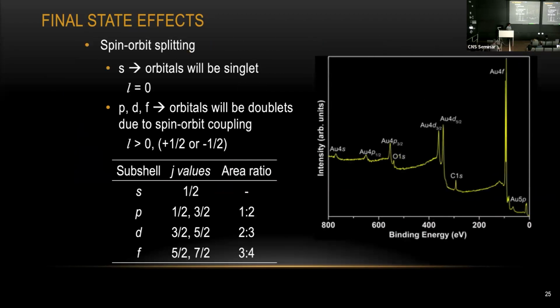And in the next couple of slides, I'm going to show you the final state effects. The first final state effect you can see is the so-called spin-orbit splitting. Again, it depends on which orbital shell you are moving an electron out from in your sample. If you're working on carbon, the signal coming out will be from the 1s shell, so you're only going to see one single peak. That's why carbon is only one single peak right here. But if you're moving the signal out from the p, d, and f shells, you might see two peaks.